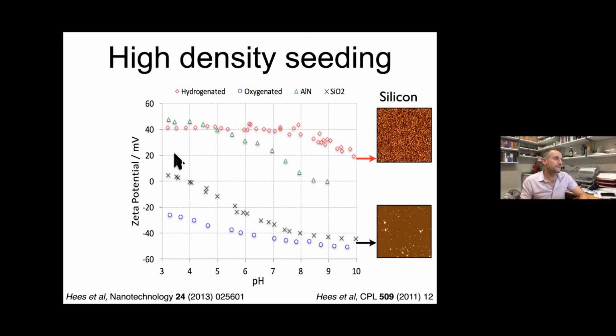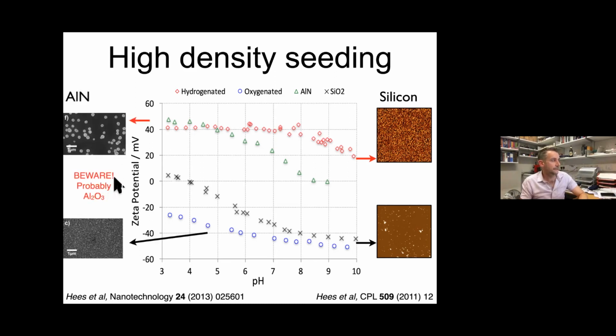So what we also did is we played with the opposite. Other materials like aluminium nitride, where you've got to think about the surface a little bit. So what I'm going to say here is a big beware, because some aluminium nitride surfaces have the opposite zeta potential, but it really depends on the face of the aluminium nitride and whether it's oxidized. And so what I'll do is I'll just show you all the data from all our papers.